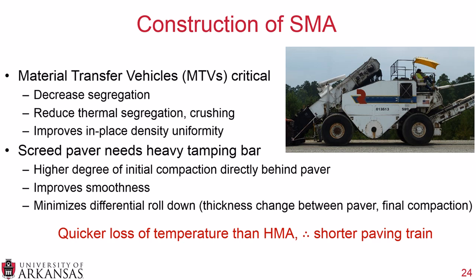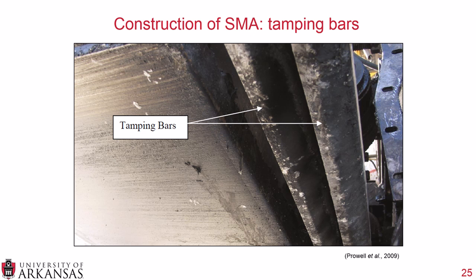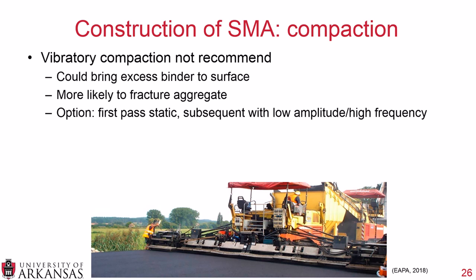Tamping bars on the bottom of the screed provide compaction immediately as material is placed through the paver, minimizing the differential between the mat thickness at the screed and after final roller compaction. For compaction, vibratory compaction is not recommended because it increases the potential for crushing of coarse aggregate and could bring excess binder to the surface. If vibratory compaction is necessary, one option is to have the first pass as a static pass and subsequent passes with very low amplitude, high frequency vibration — but in general, vibratory compaction is not recommended.